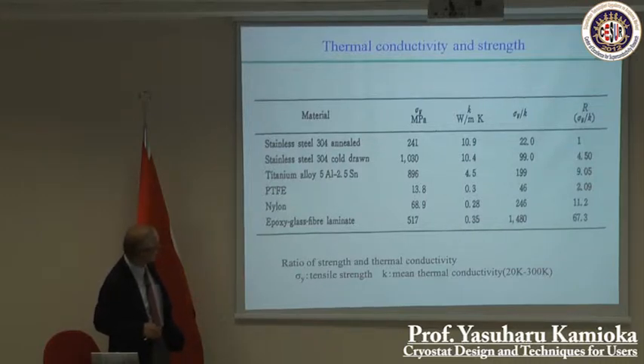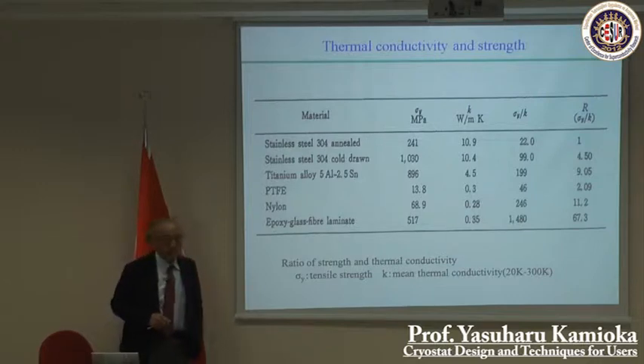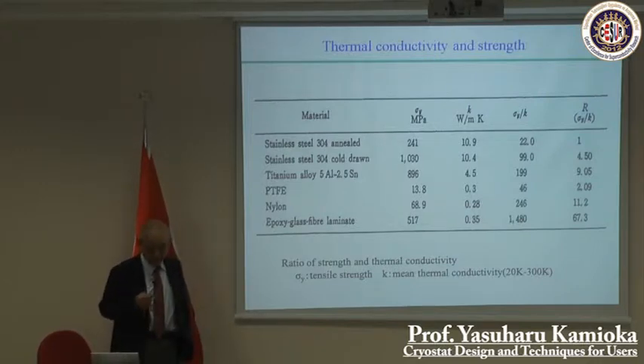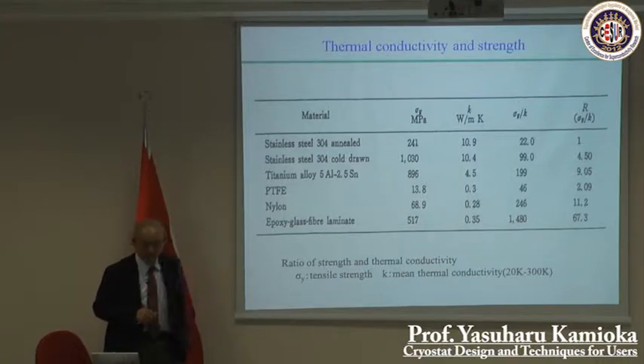But if we use epoxy glass fiber, I mean, like G10 type material, this is a very high number compared to the stainless steel. So usually you use stainless steel, but you have to think about G10 material. It's very strong when you think about the thermal conductivity.